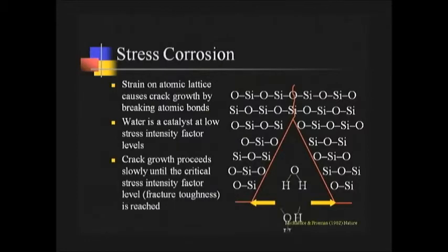And water helps out with this. So the water is coming into the tip of the crack and acts as a catalyst. And you know, water is a polar molecule, and the oxygen has a slightly negative charge on it. Hydrogen has a slightly positive charge. And so the negative charge on the oxygen ion in the water is attracted to the positive charge on the silicon, +4 charge, and it attaches, and positive hydrogen attaches to the negative charge on oxygen, and the water reduces the energy necessary to split the silicon and oxygen apart. So it's a catalyst for stress corrosion.